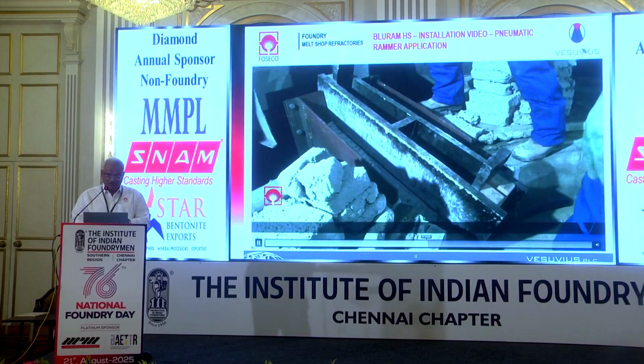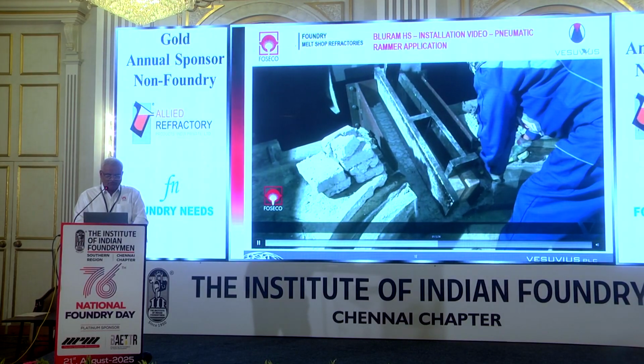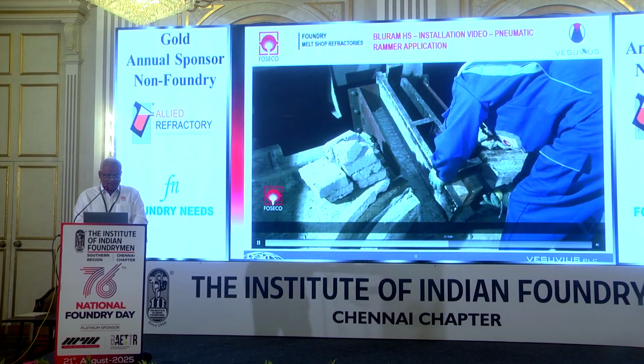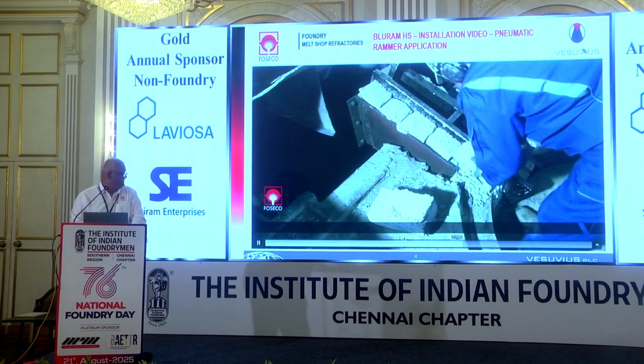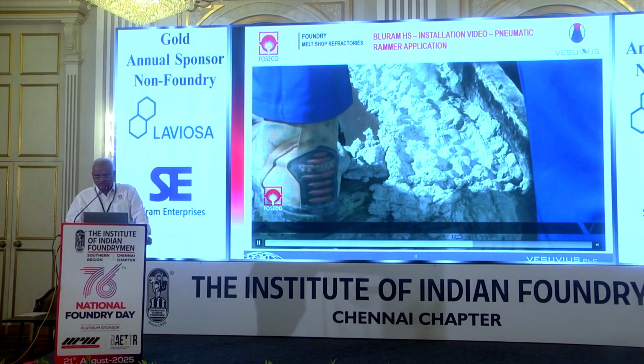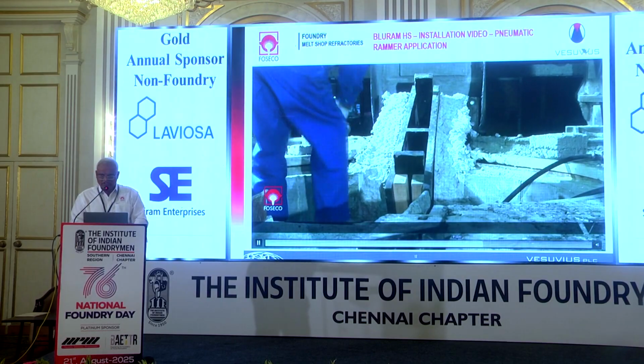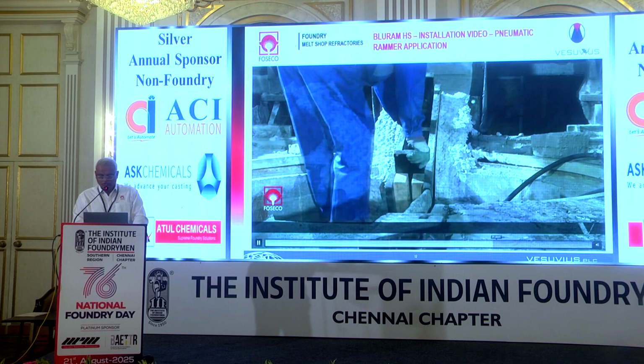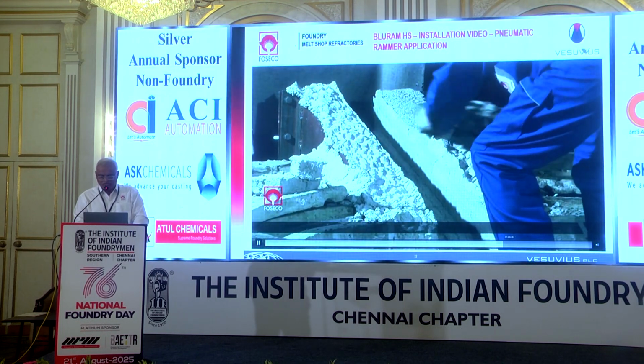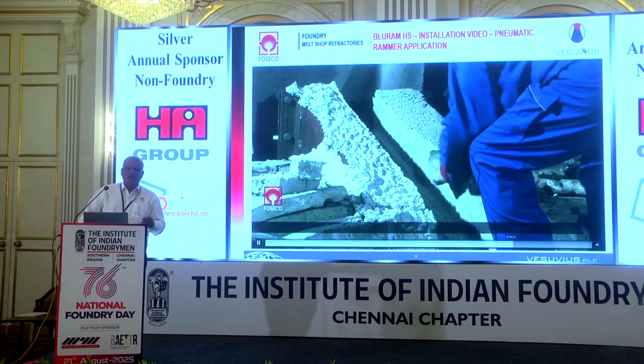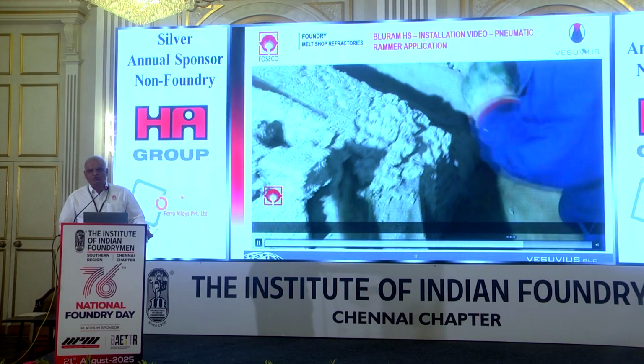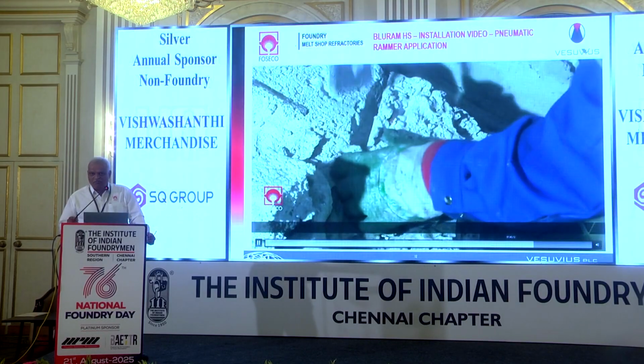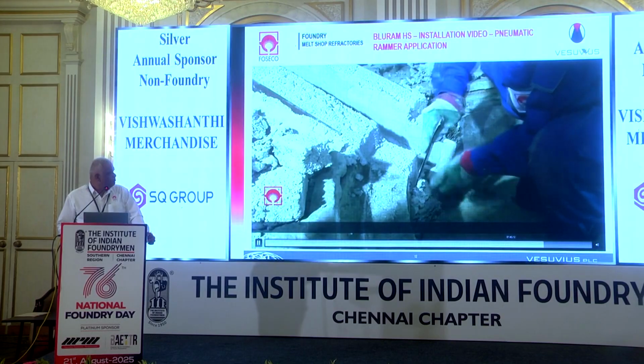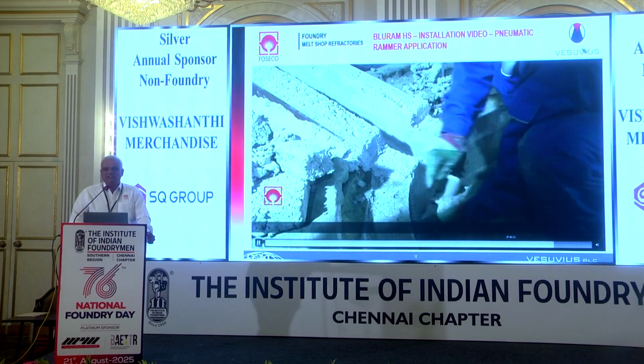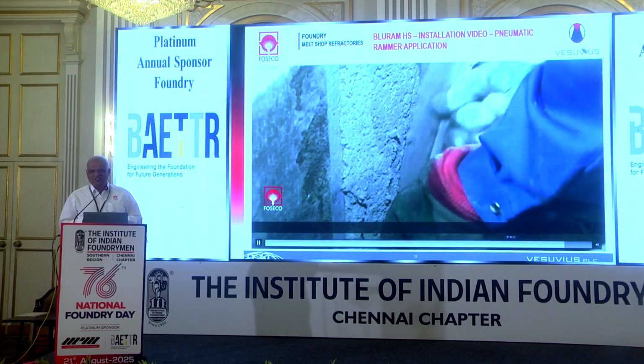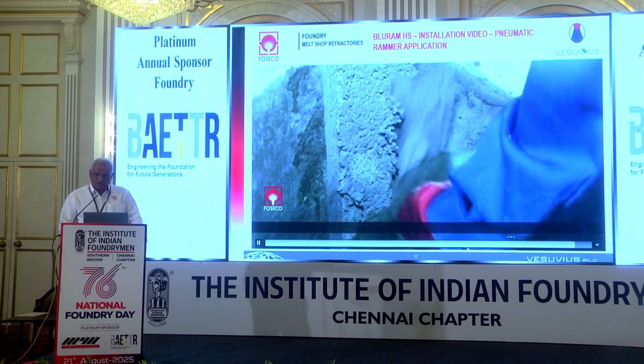Here they are putting the former to get the shape of the spout. Then again from beside that former they are putting more material, vibrating it with the vibrator. As the furnace size is big, but if it is a small furnace, we can do it by manual ramming also. It is that much soft material and easy to use, and you can get any kind of shape with this plastic material. This is phosphate bonded material, so it can be dried easily. It has a non-wetting property also, and good strength, which can stand mechanical attacks. It also absorbs thermal shocks, and because of the non-wetting property, slag sticking is very less. So this material is very helpful for the foundrymen for making the spout and top.